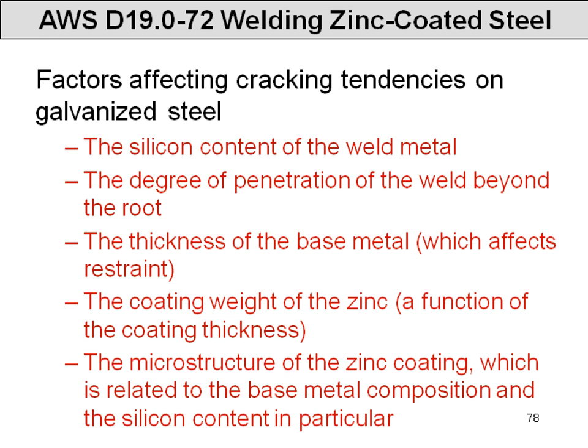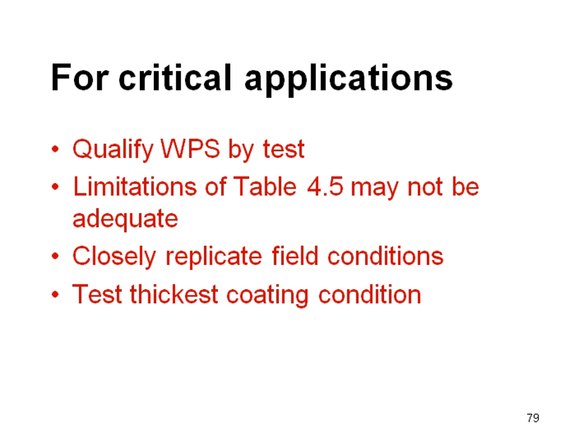So I want to be practical. I want to give you some good information because you have a job to do, and you have a structure that's going to be galvanized, and you need to weld on it, and you want to be certain that you're going to get the strength out of the connections you're looking for. So here are my suggestions for critical applications. Now you have to define what a critical application is. And that gets into redundancy, its loading on the structure, its consequence of failure. You define what's critical. But if you decide you have a critical application, the first item is I suggest that you qualify the welding procedure specification by test.